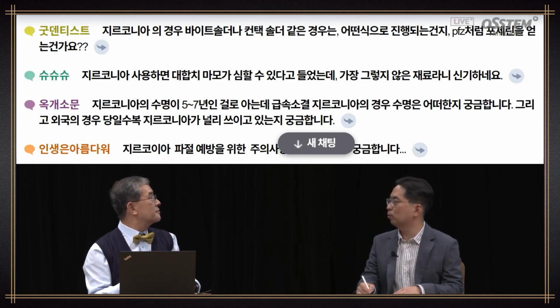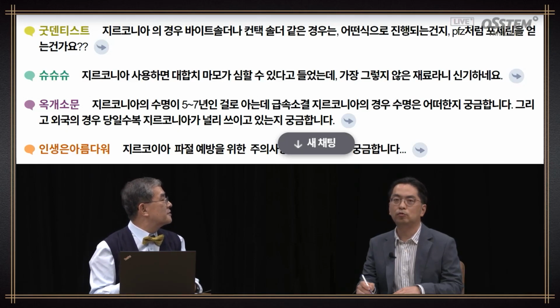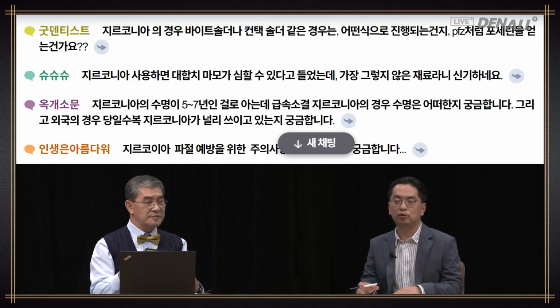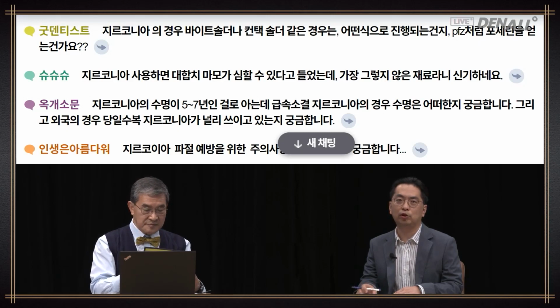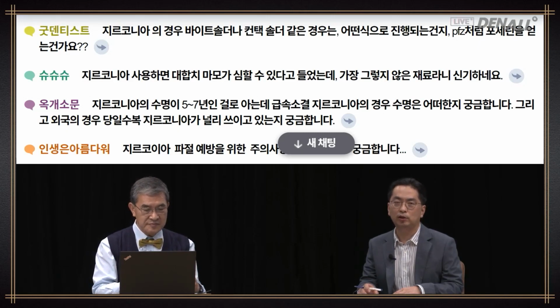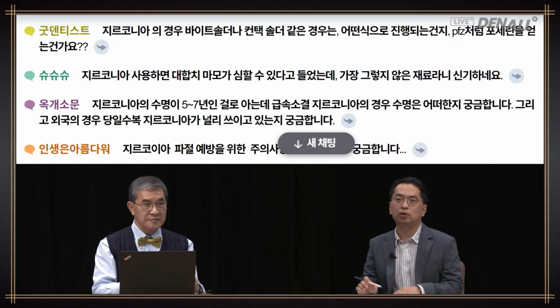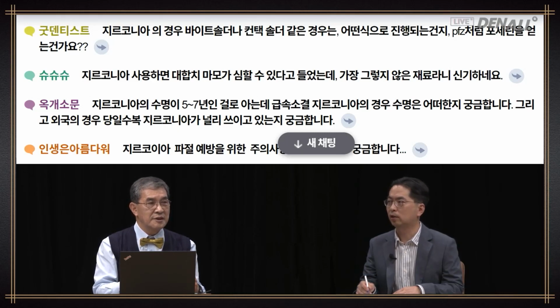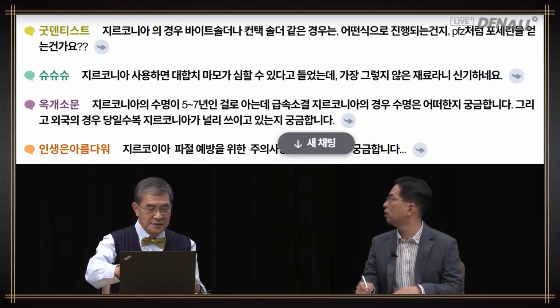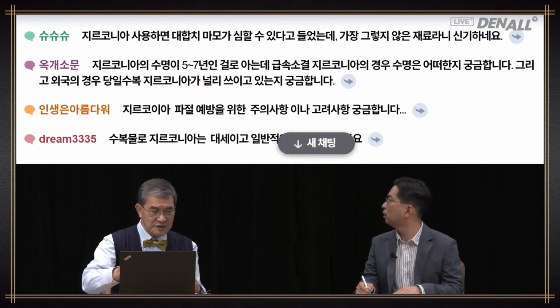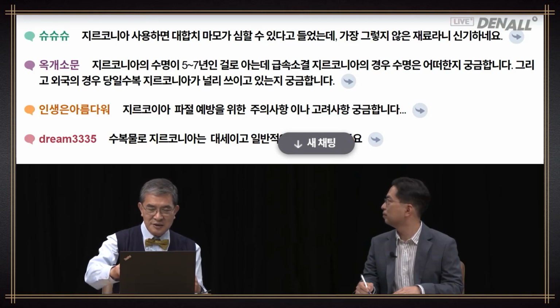Yes, that is correct. Basically, after you sinter zirconia, you can either do polishing or glazing. In the case of glazing, you can do it very thinly or you can add thickness. You can add contact using glazing. Shu, I heard that if you use zirconia, antagonist wear can be very severe, but you're saying that it's otherwise.